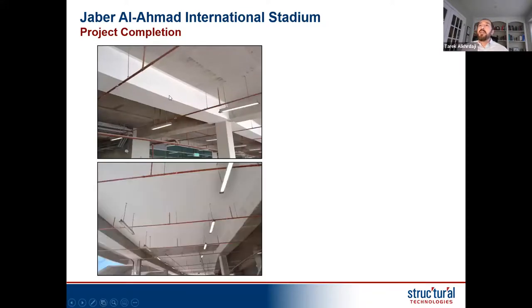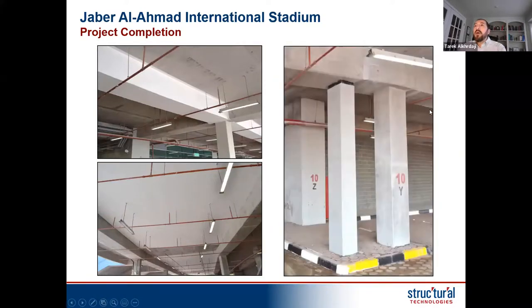This is after it was coated and finished. Most of the locations, this is the beam you can see in here. This is the slab. So this is what I mentioned: when you apply the coating, you can fully protect it and it's really not that visible. Another thing that was done, since we're talking about strengthening, is that in some of these locations where the beams were sliding, it was very hard to come up with a solution other than installing new columns that went all the way down with a new foundation and a big bearing pad, neoprene, that allows it to take the movement, while providing additional vertical support to these beams. That would relieve some of the stress that was going on at these joints, on these corbels, let's call them.